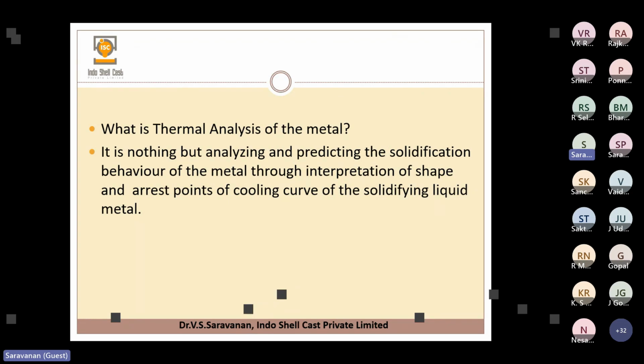So for that, this thermal analysis software is giving a helping hand to some extent. I'm not saying that it is going to solve the entire problem, but it will help to some extent to come out of this issue. At least we can identify some areas to correct. So here, the ductile iron is a very sensitive material, as I told earlier, and the solidification range of ductile iron is actually a short freezing range.